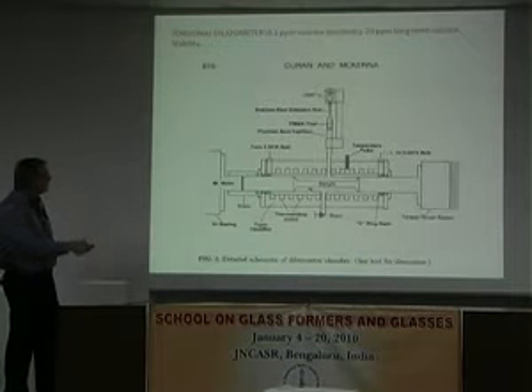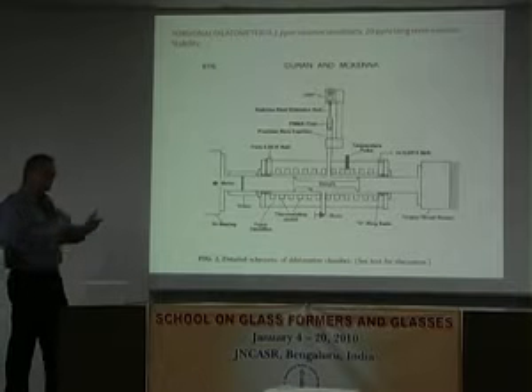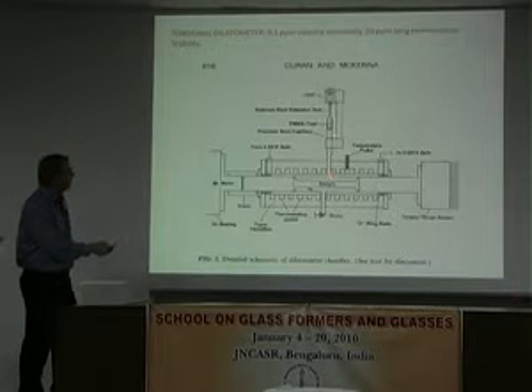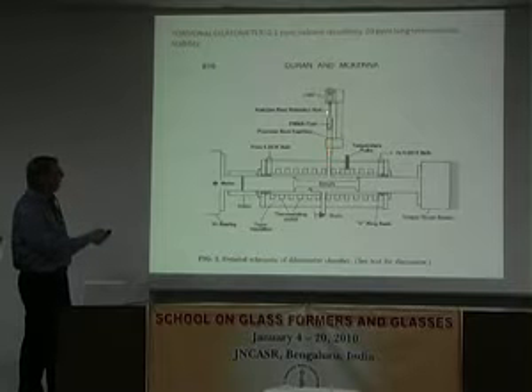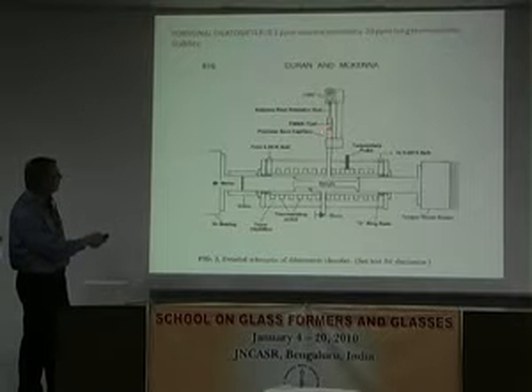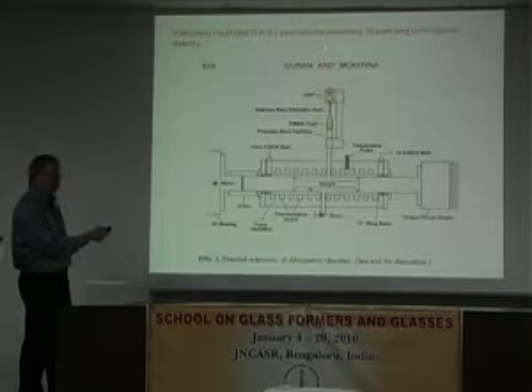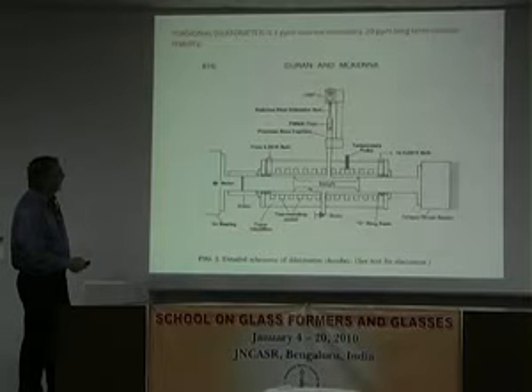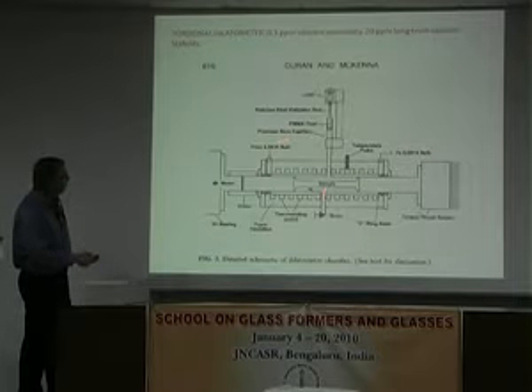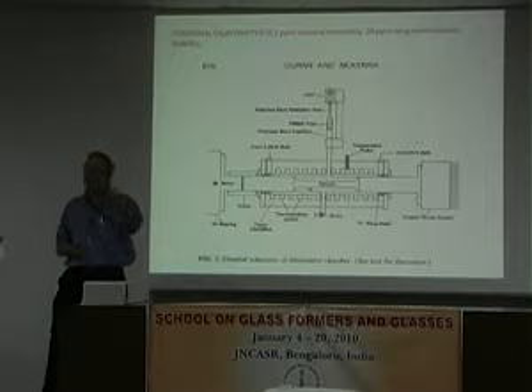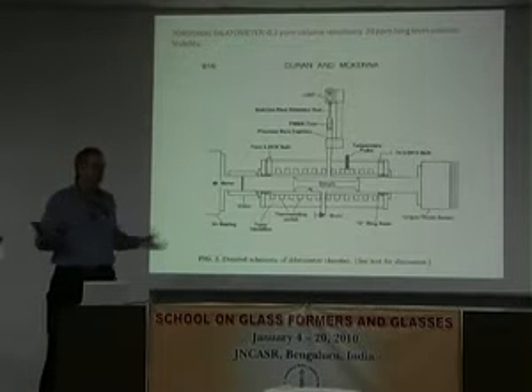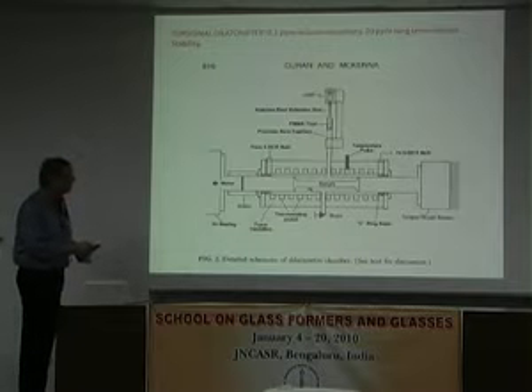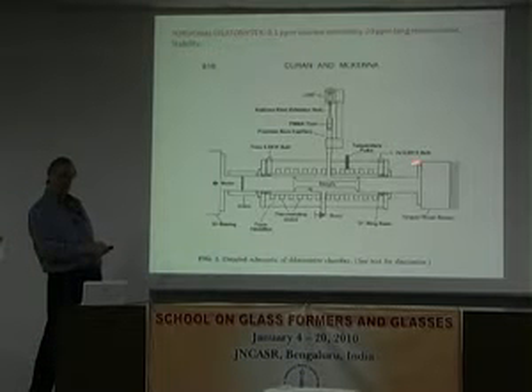So we fill it with mercury, and then what we're going to do is twist the sample and watch the mercury go up a capillary with an LVDT with a float, so it floats on the surface of the mercury. And we can measure submicron displacements of the capillary. And so then the question is, how well do we do? Well, of course, what is the first thing you think of when you think of mercury in a capillary? It's a thermometer. So in fact, that's the reason why we need this good temperature control.